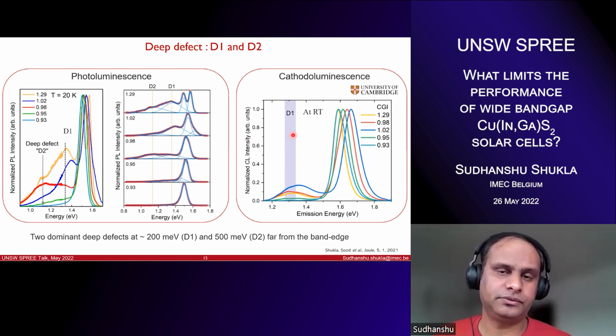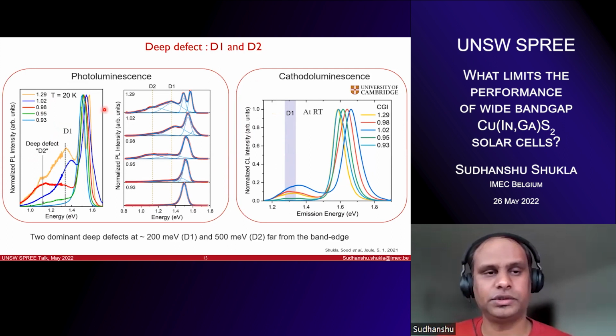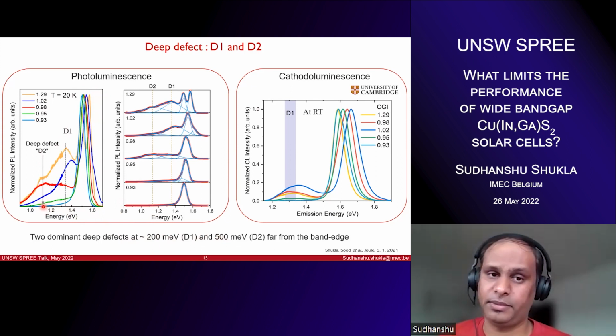And then we went to low temperatures to try to investigate more about the defect physics of the material. So what you are looking at right now in this photoluminescence plot, it has been taken at 20 Kelvin and normalized to this band edge. What you see is the appearance of these two defect bands, which I have marked as D1 and D2. And D1 is actually as far as 200 meV from the band edge. Don't confuse this as a band edge, because at low temperature your band gaps might be different than this, which I don't know. So this is roughly 200 meV far from the band edge, and D2 is roughly 500 meV far from the band edge.